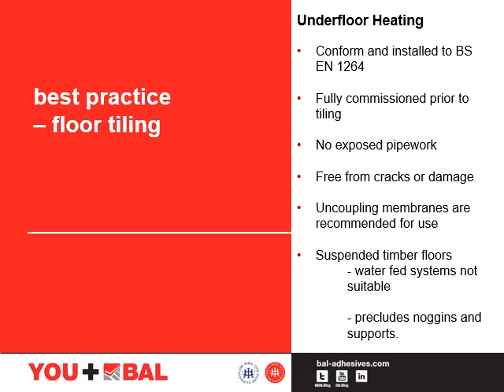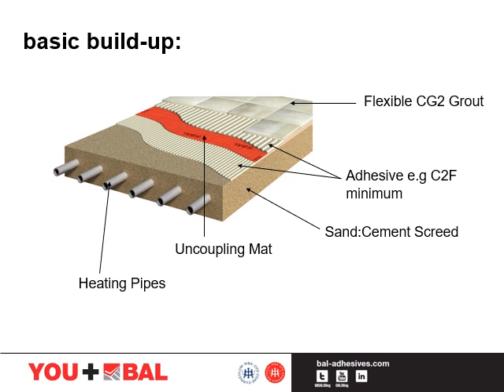The underfloor heating in any installation needs to conform and be installed to British standards. It needs to be fully commissioned prior to tiling with no exposed pipe work or cracks or damage present. Uncoupling membranes are recommended for use with all underfloor heating systems with natural stone. The Stone Federation gives us safe guidelines on this. Suspended timber floors containing water-fed systems are not suitable for tiling, as heating pipes preclude the installation of noggins and supports. When using natural stone over an underfloor heated screed, the specification calls for a minimum of C2 tile adhesive and a minimum of CG2 grout. It is also worthwhile specifying an uncoupling mat as per the recommendations from the Stone Federation.